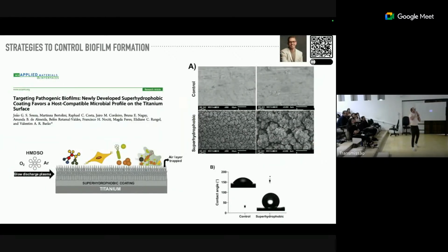It's like this. So I'm showing now. I forgot to say that I have here the photo of the main student that ran these experiments of the paper, and also the QR code, so you can just use your cell phone, and then you're going to get the paper in full. In this paper, we developed a one-step superhydrophobic coating. Of course, if you go to the literature, you're going to see several hydrophobic surfaces, but by that time, we didn't find any surface that was superhydrophobic by just one step. In this case, we use a plasma surface treatment in an environment containing oxygen and argon and hexamethyldisiloxane, and we developed a very rough surface with only one step. We do not need to roughen the surface before. Only the plasma by itself promotes this cauliflower surface.